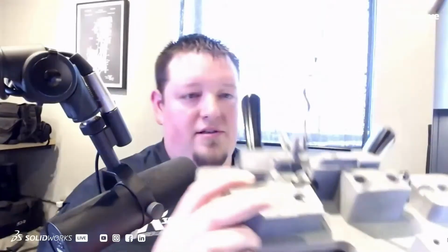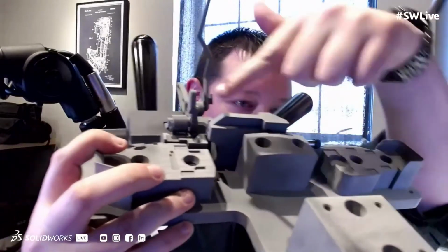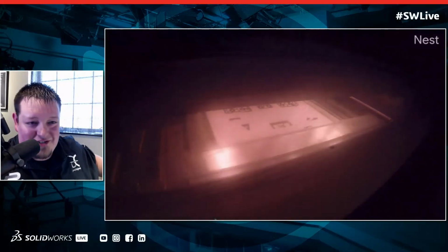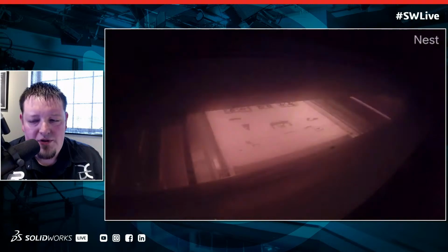Yeah, so this is from Tuesday night, and if you look across the upper edge of the build volume, you can see 3 honeycomb parts sitting back there. That is actually these components here, here, and here. This was only a half full build because it was such a rush to get it ready for today. About 8 or 9 inches, and it ran for I think 9 hours. Then we cooled it, so that would have been Tuesday night. Then yesterday, Wednesday, we cooled it for about 12 hours.